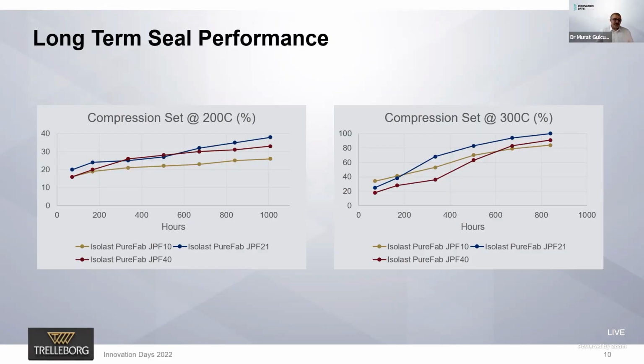in both cases, we've done this test extremely long. Actually, we have even longer tests, up to, I think, 4,000 hours. So you can see all of the materials still don't deform too much. So the lower the results, the better the performance in compression set. So you can see at 200 and 300 degrees, our materials can retain their sealing performance for really long